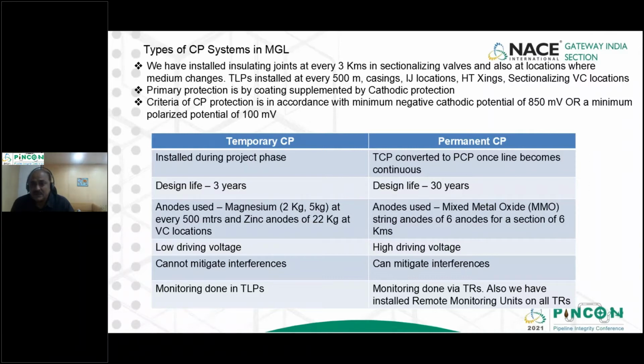The primary protection is coating, and we supplement it with cathodic protection. The criteria for cathodic protection is in accordance with a minimum negative voltage of 850 millivolts, and that's the first criterion, or a minimum polarized potential shift of 100 millivolts. So this is our condition for CP protection. The temporary CP is installed during the project phase, and after the project is completed, we install the permanent cathodic protection once the line becomes continuous.